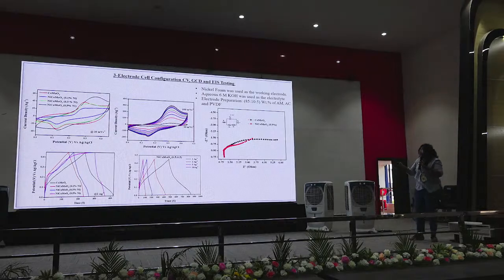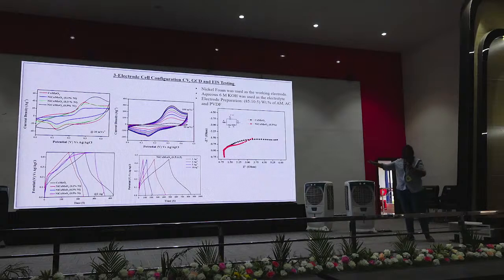Here the galvanostatic charge discharge of the cobalt molybdate with different percentages of nickel has been done. Here you see the cobalt molybdate has a higher discharge time compared to that, but the nature of the curve that is obtained is the correct shape of a GCD profile. So this is one thing I have observed here. Coming to the part of